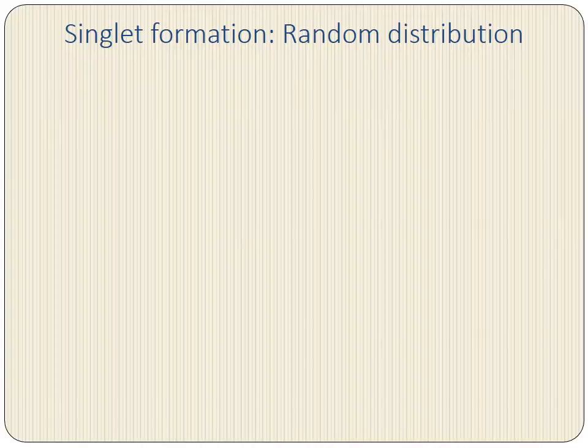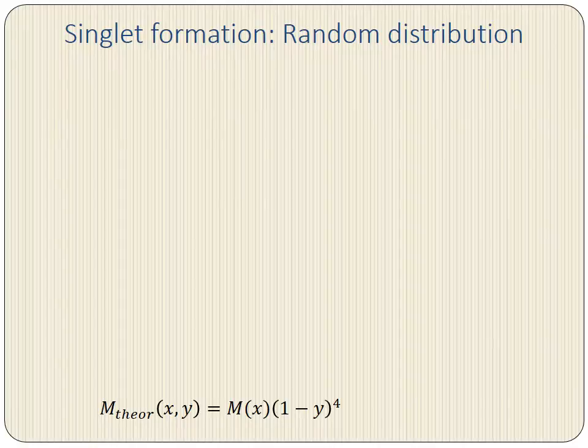Now, since we are in the dilute limit, we're going to ignore clusters of 3 or more manganese atoms. It should be noted that including them will just give a small correction. When we work out the combinatorics, we obtain the following expression, where we see that the magnetization depends on the hole doping level, which in principle we can obtain from our density functional theory calculations, and then the expression also depends on Y, which is the manganese doping level.